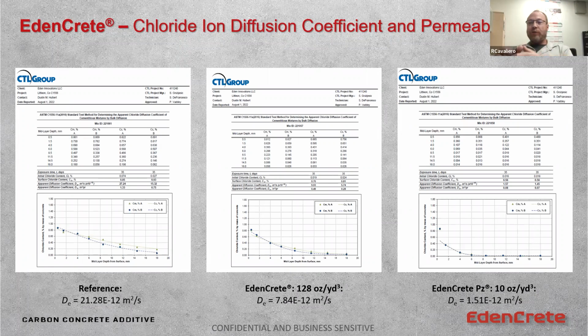We take a cylinder, we coat the sides, we put a 3% chloride solution on the surface, and we let it sit for a period of time. We then use a mill, and we mill off 1 millimeter or 2 millimeter sections, and we titrate that for levels of chloride as a function of depth down into the sample.